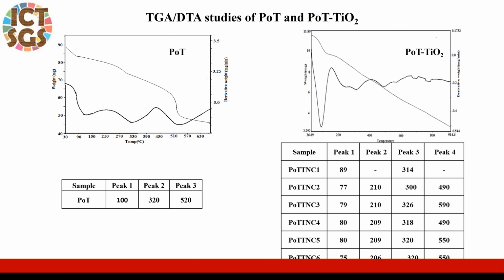The thermal behavior was studied for both polymer and polymer metal oxide nanocomposite. This figure clearly indicates that the thermal stability of the polymer metal oxide nanocomposites is much higher when compared to the polymer.